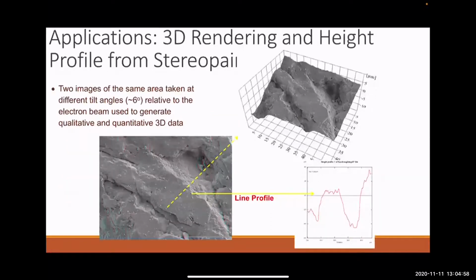But if you take two SEM images at different tilt angles, so you tilt the sample back and forth and take a couple of images, then you can combine that and get back that missing third dimension. So you can get back a height, for example, and so see how deep that particular trench is in a quartz grain. And this is a nice example where you want to measure heights, and typically you might want to do that with an AFM, an atomic force microscope. But in this case, being a quartz grain, it's a little too rough and irregular to get the height in that manner. AFM really uses, your samples have to be quite a bit flatter. And so this was an ideal case to be able to use the SEM to get back a height profile.